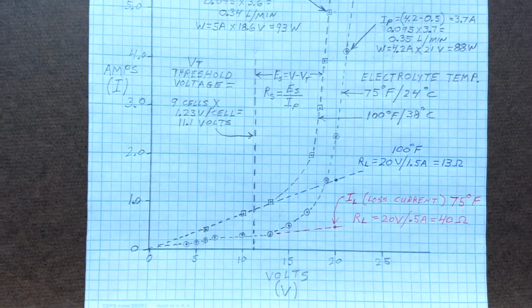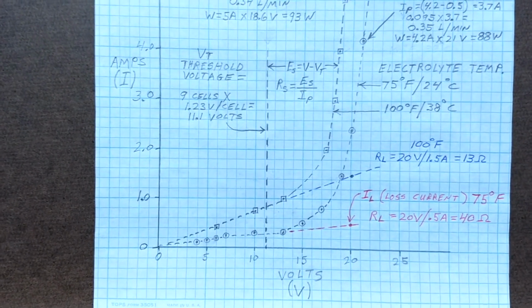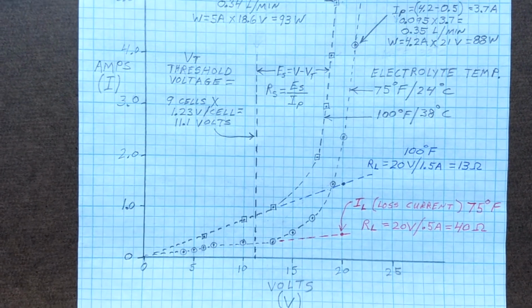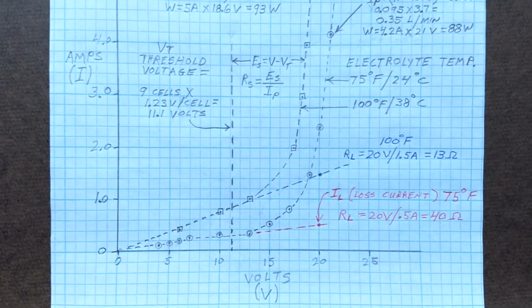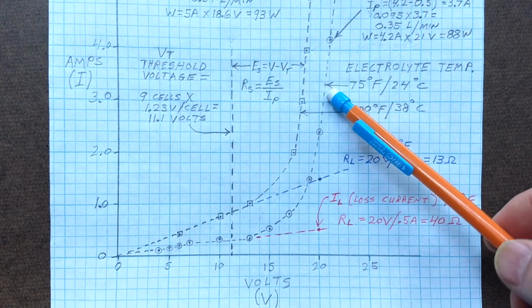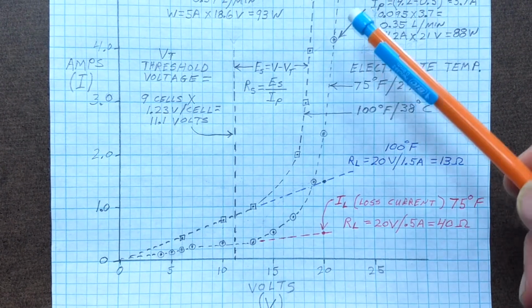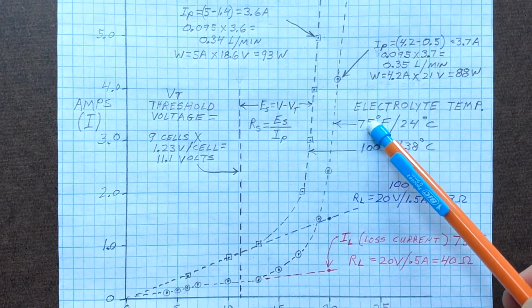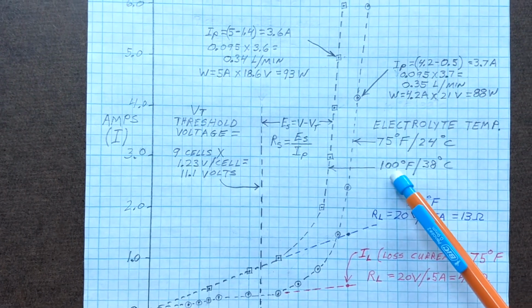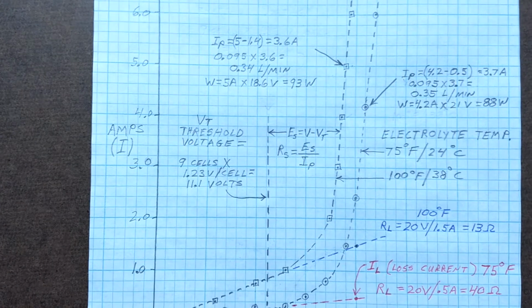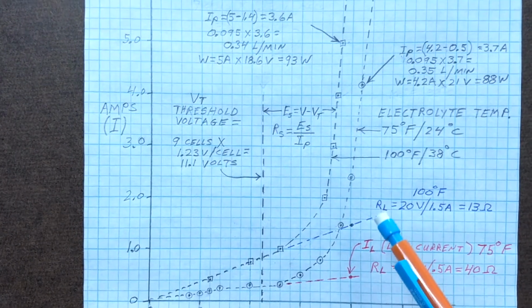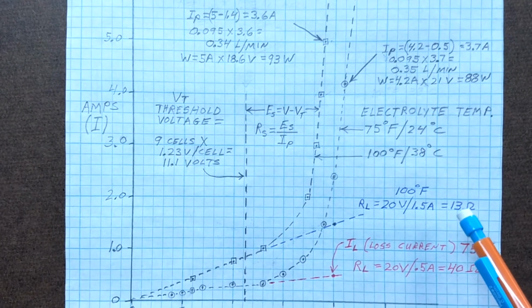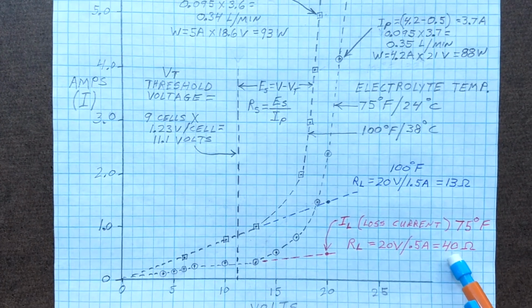Okay, I've added the high temperature curve to the original room temperature curve, and it's getting kind of busy, but I hope you can see what's going on here. This is the original room temperature curve, and the electrolyte was about 75 degrees Fahrenheit when that curve was taken. Then after running for many hours, the electrolyte had gone up to 100 degrees Fahrenheit. So our bypass current increased, so our equivalent bypass resistance was now down to 13 ohms, whereas originally it was about 40 ohms.